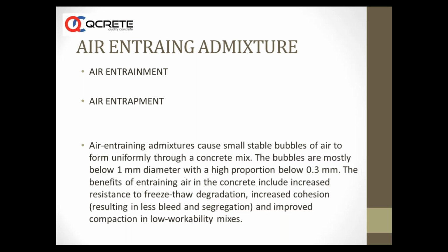Whereas air entrapment, which is a physical action of trapping some amount of air when concrete mixing takes place - here the entrapped air bubbles are bigger in diameter, irregular, spread over all across the body of concrete non-uniformly. Whereas with air entrainment, the air bubbles are seen uniformly, spread in a uniform way in the body of concrete.